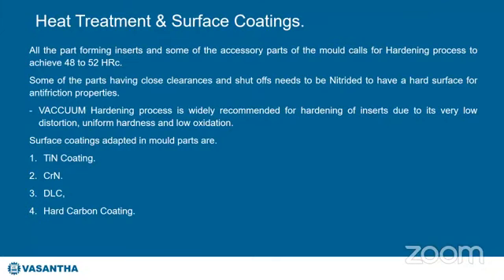Some of the parts having close clearances and shutoffs need to be nitrided to have a hard surface for anti-friction properties, like the sliding elements or moving parts in the mold, which generally wear out soon. So we do nitriding for it, which forms a smooth hard layer on it and enhances the anti-friction properties of the insert.